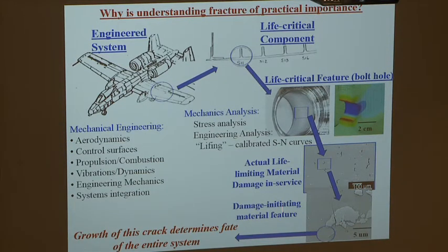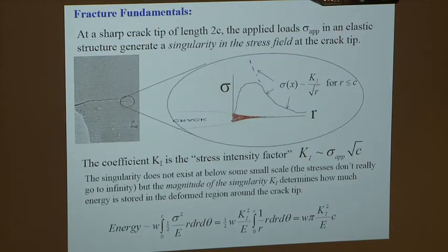problem, and we have to understand what's going on here, either to make better predictions of what's going on here, or to improve the material, not only get rid of these particles, but understand how to stop the cracks, or what kind of textures are necessary, or whether there's environmental effects, because it's this problem way down here that controls the life of the component. Okay? So we're going to try to go down and pay a lot of attention to what goes on at this scale of the crack tip.